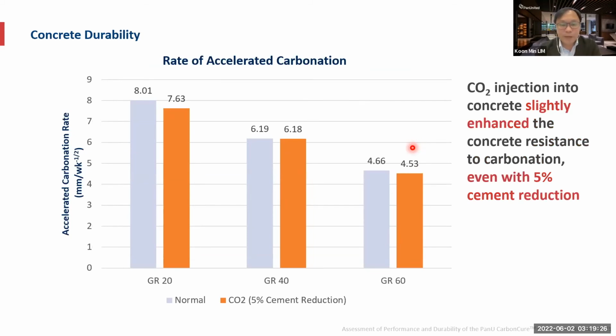And the concrete durability, which is of major concern for most developers and also for consultants, right, is the concrete durability results that I'm going to show. So again, the gray color is the normal concrete. The orange one is the CO2 mineralized concrete with 5% cement reduction. You can see the rate of accelerated carbonation. The resistance to carbonation is actually enhanced, a slight enhancement. A lower number means more resistance to carbonation is being shown, from grade 20 to grade 60. So by comparing both normal concrete and CO2 concrete, the CO2 mineralized concrete has a slight enhancement